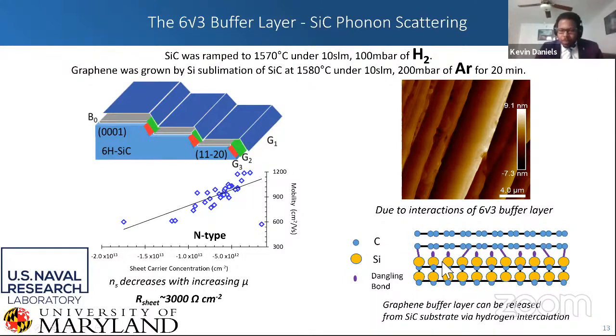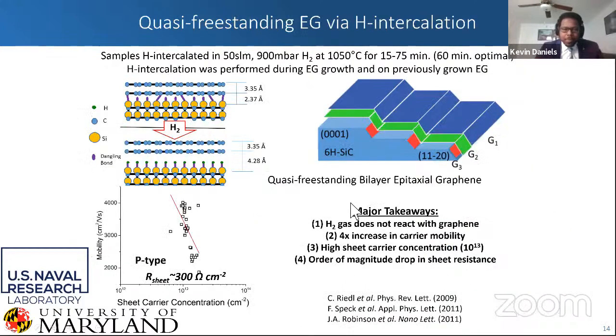So as shown here, we have these dangling bonds coming from the silicon atoms that are binding this first layer of graphene that's been formed on the surface. Now, one of the things we can do is introduce hydrogen. What the hydrogen will do is go in and passivate these bonds, and by passivating these bonds, we release this electron-phonon coupling as a result.